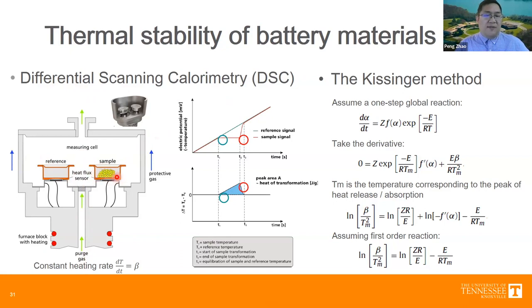But as there can be physical chemical transformation within the sample, eventually when certain process happens, the sample temperature is going to deviate from the reference temperature. So by calibrating this temperature onset for the deviation, and also by calibrating this peak area using some standard samples, we can calibrate the onset temperature and also the heat of transformation. And that's the working principle for the DSC. And people are using this equipment to study the thermal stability of battery components.